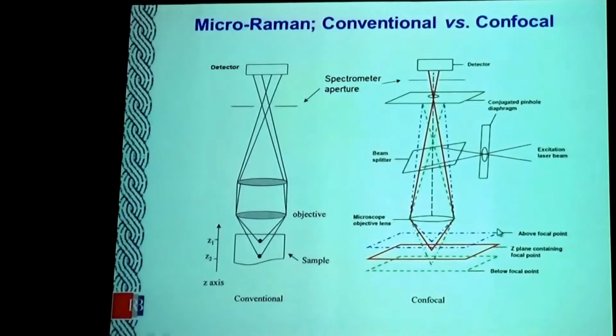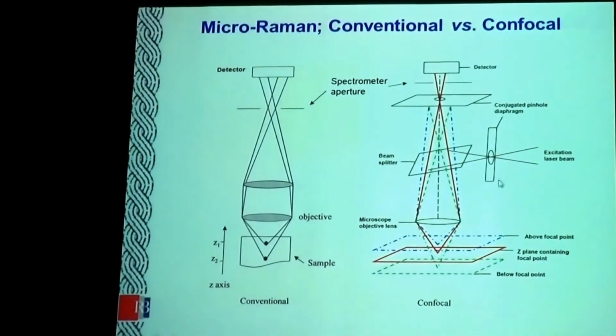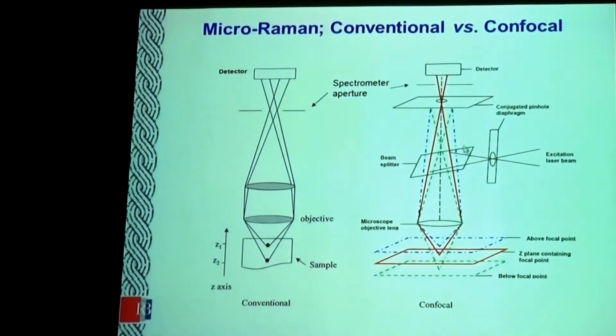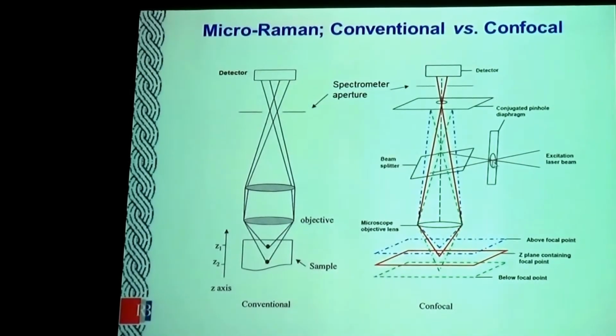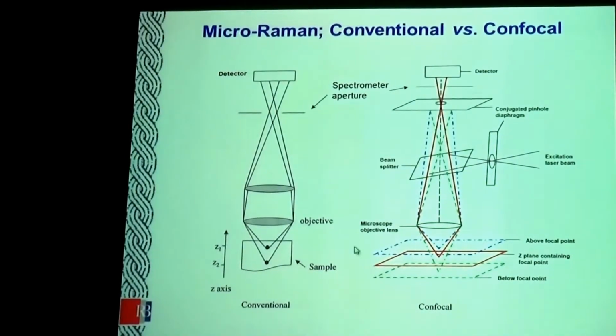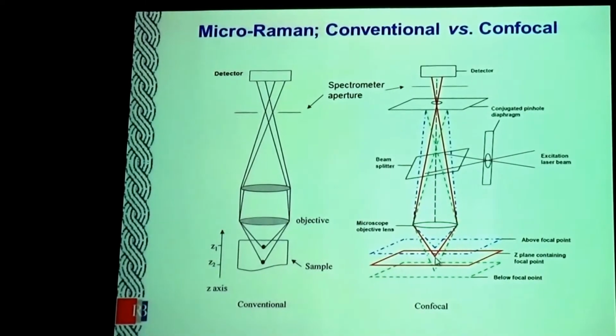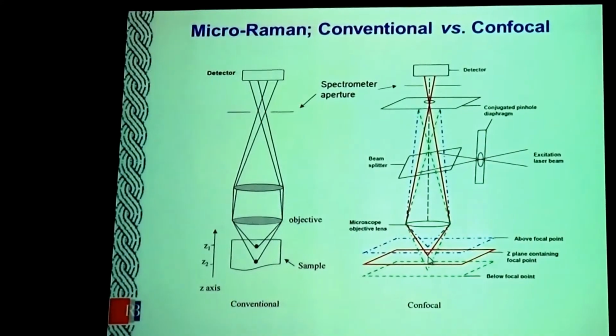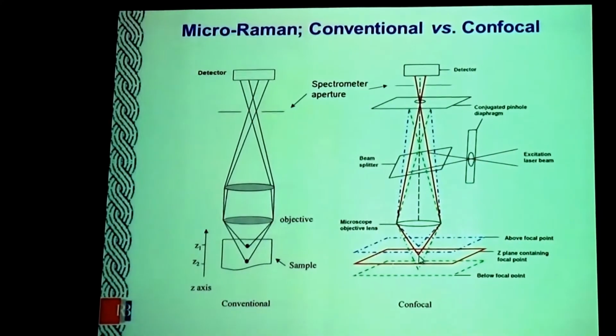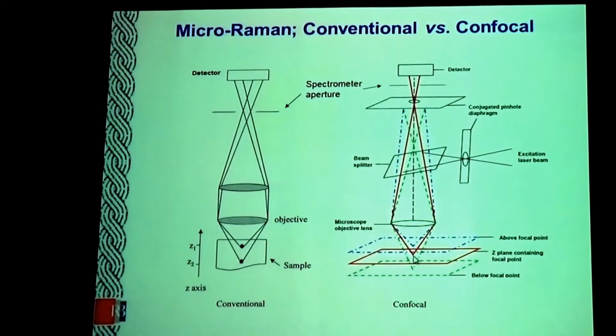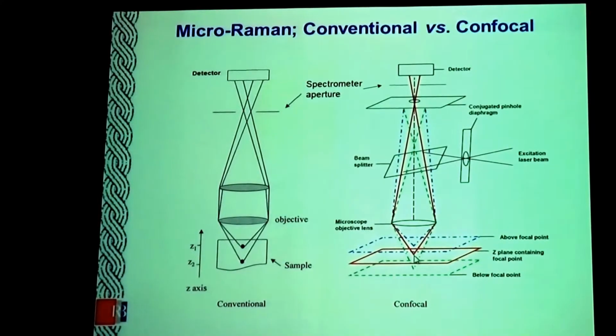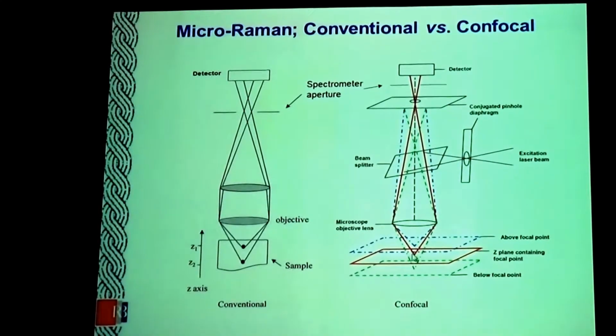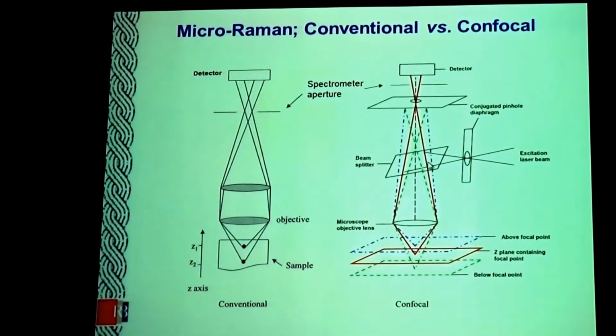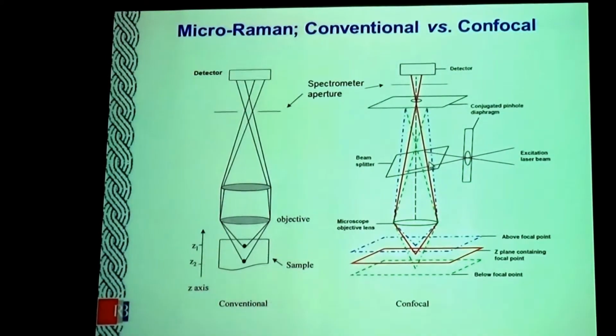And especially it's useful to have confocal Raman, because in a confocal system we have a very small focus. Therefore, if we have a multi-layer sample - the sample of course should be transparent, otherwise you cannot go deep in the sample with your laser - then you can do depth profiling and measure your layers in the sample.